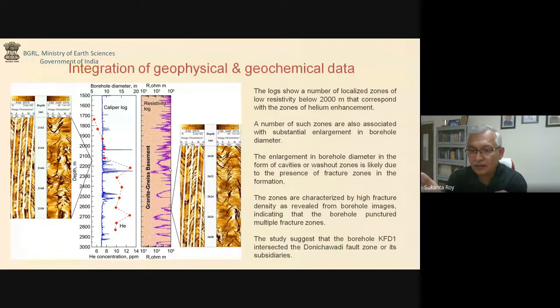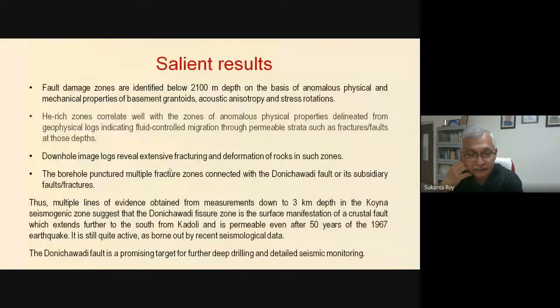And so essentially, a number of such zones are also associated with substantial enlargement in the borehole diameter, which means that the borehole really passed through big fractured zones below 2,100 meters. The enlargement of the borehole diameter in the form of cavities or washout zones is likely due to the presence of fracture zones in the formation. And these zones are characterized by high fracture density, as you saw from the image logs, indicating that the borehole punctured multiple fracture zones. Therefore, the study suggests that the borehole KFD1 intersected the Donichawadi fault zone, or maybe its subsidiary faults. So this was a very clear indication.